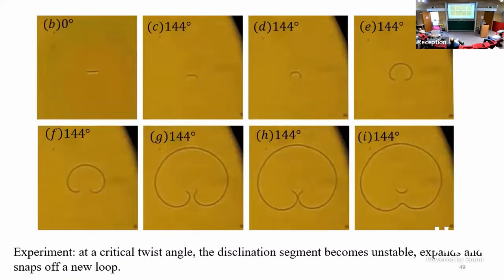They only snapped off one loop, but I will tell you, if you twist it another 180 degrees, you get another loop. Twist another 180 degrees, you get another loop. So each of these, again, inside the loop, the material is untwisted by a half twist relative to what's around it. And again, if those defects go out and they annihilate at the free surface, then there's no back stress. It'll just keep producing forever.